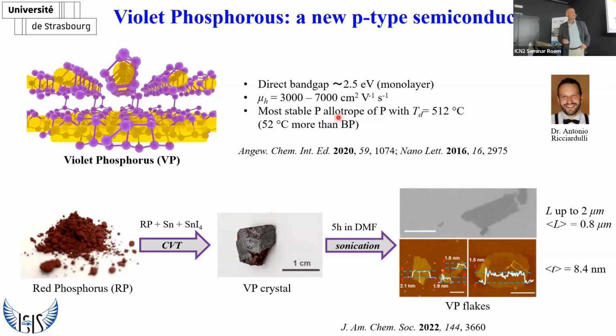And actually, what happened to this violet phosphorus, in a nutshell, is that violet phosphorus is much more stable in air than black phosphorus. And this stability is also used in the synthesis of the violet phosphorus: given the higher stability in temperature of the VP compared to BP, one uses a temperature during the CVT such that it decomposes any kind of black phosphorus byproduct.